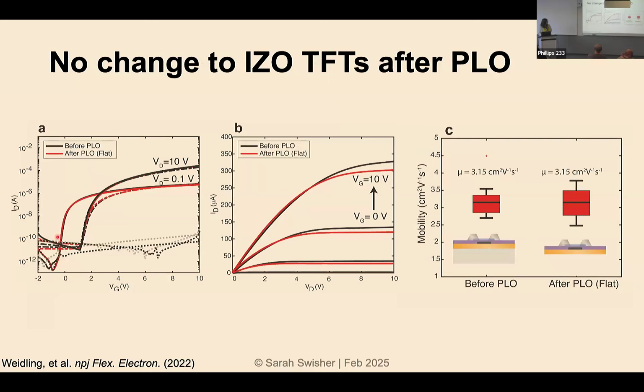So we see a bit more hysteresis in these devices and a little bit lower mobility than what we saw in the previous devices because of that, because these are on plastic, as I mentioned. We can't push this temperature quite as high. But we see that there's basically no change before and after the liftoff. The mobility stays about the same.